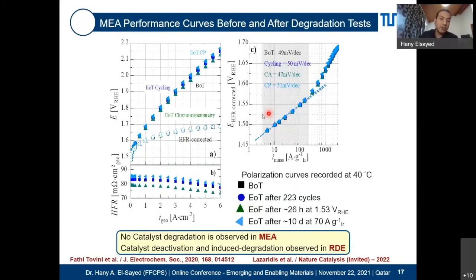So we put all these together, and this is basically the UI curve. And this is the performance curve, or sometimes people call it the performance curve of electrolysis. You can see the beginning of life curve and end of test for chronoamperometry, for potential cycling, and for constant potential. All of them are on top of each other. What does that mean? It simply means that the catalyst that we tested in this study is basically super stable if you estimate the stability using an MEA. But if you take the catalyst and apply the identical conditions in RDE, the result is it's not a stable catalyst. So again, there is no catalyst degradation in MEA, but the catalyst significantly degrades in case of the RDE.